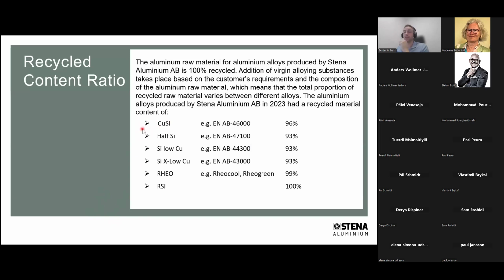So basically it goes from the copper silicon alloys, that's for instance the 46,000 alloy. That is, I would say, the most common foundry alloy today. And there you have a 96% recycled content, meaning that it's 4% primary alloying elements that you need to add, or that we add in when we produce this on average then. And then it goes down in the lower copper content containing alloys. So this half silicon is, for instance, the 47,100, it's 93%.